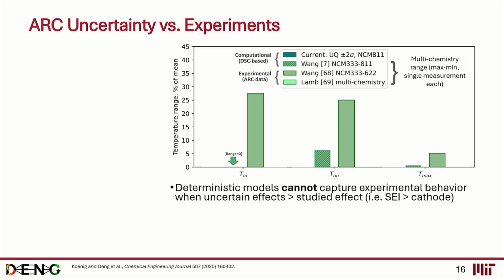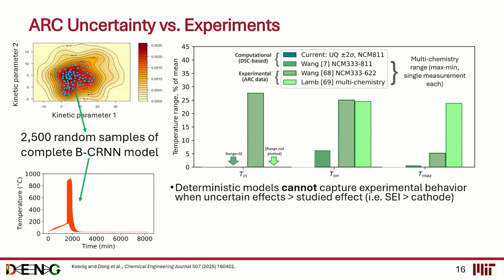So if you do it in the deterministic way, you wouldn't be able to capture the influence because in your model, nothing should depend on the cathode. And this is not a single case. If you look at other metrics, such as the onset of thermal runaway, as well as the maximum temperature, we cannot capture the dependence on the cathode chemistry.